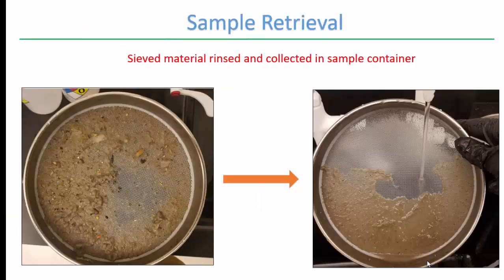So the photograph on the left is of a typical influent sample. You'll see large debris, a large mat that's largely toilet paper that's binding on the filter, while the one on the right, that's a much finer mesh. That's probably about a 25 micron sieve, and it's free of debris, still has some cellulose material, but a lot of algal material.